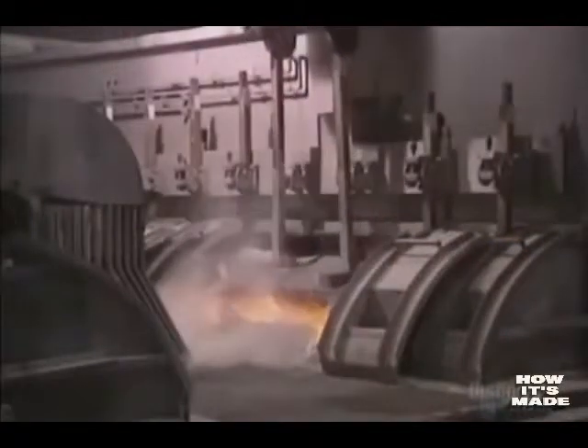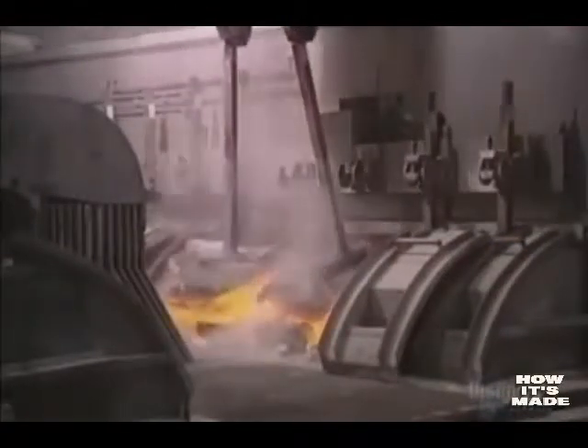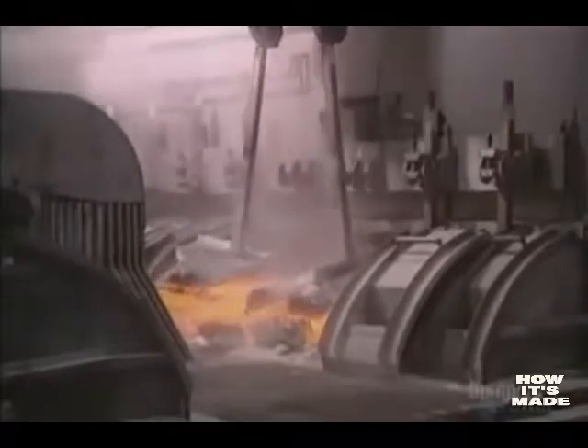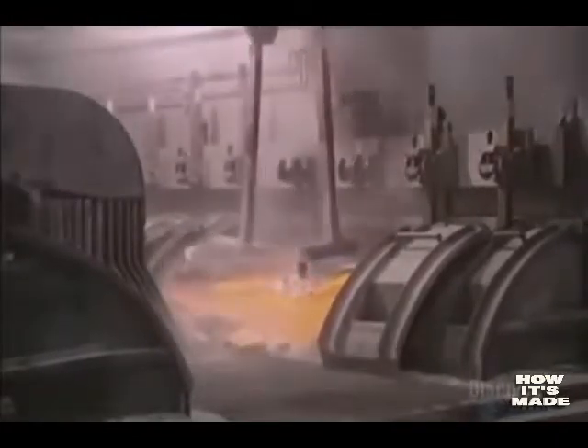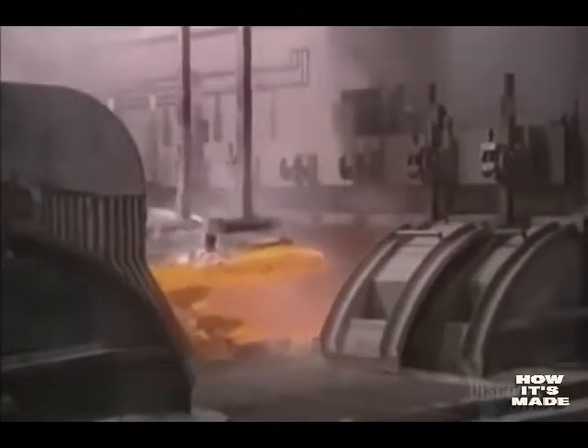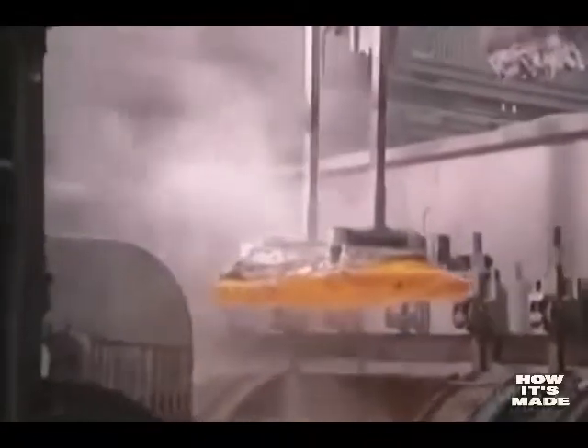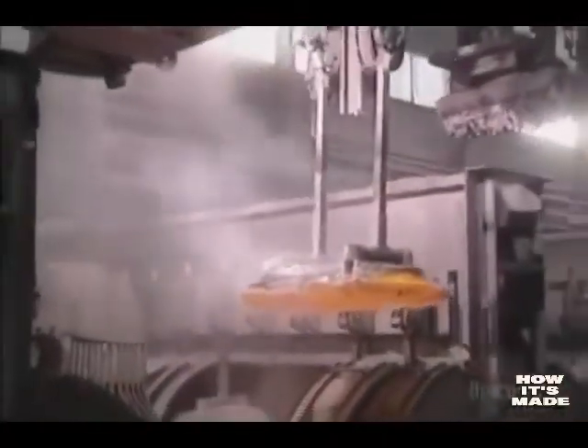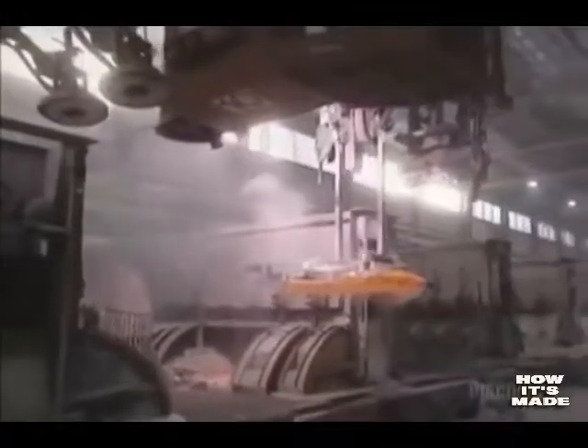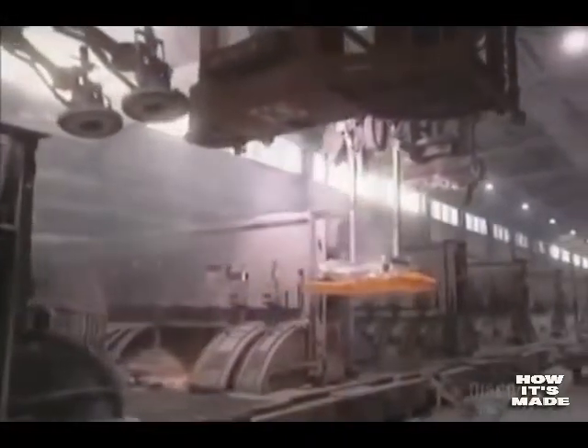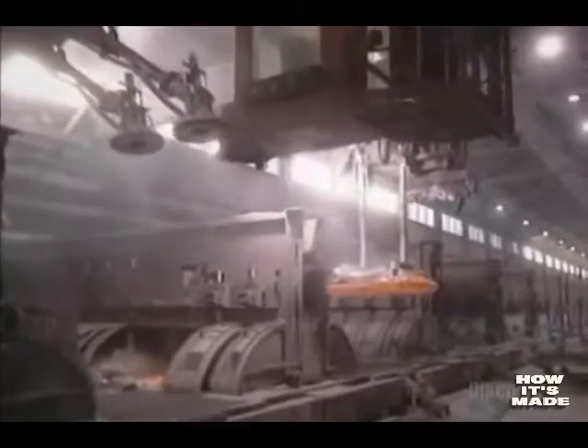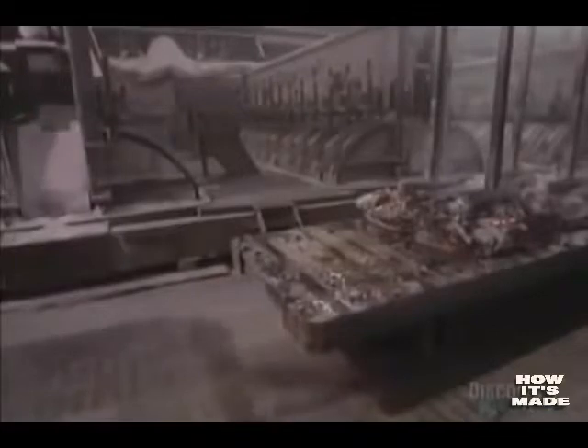Via the process of reduction of the alumina at 950 degrees centigrade, the anodes lose volume and will have to be replaced. It's a continuous operation. Each anode has a lifespan of about 20 days. Spent anodes are recovered from the pot with this overhead crane and carried off to be recycled. They clean the aluminum rods, which will then be reused.